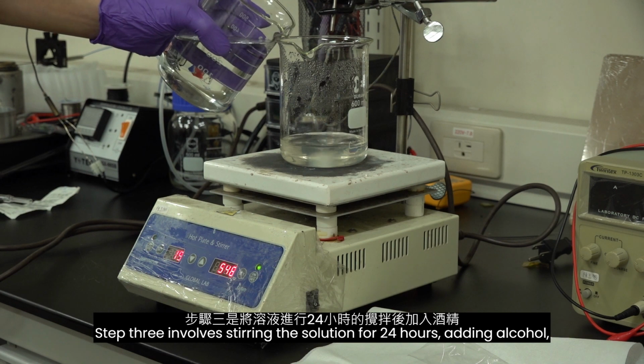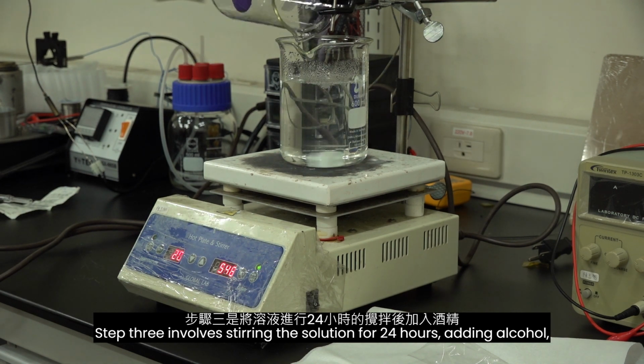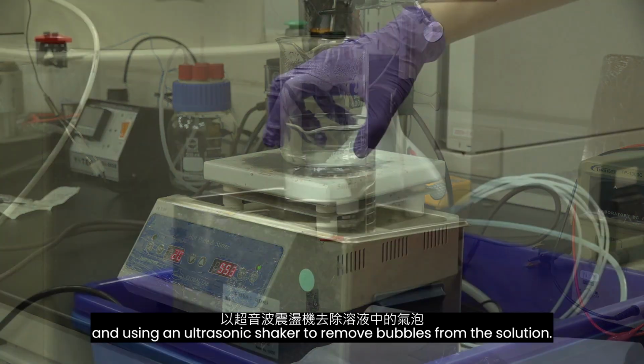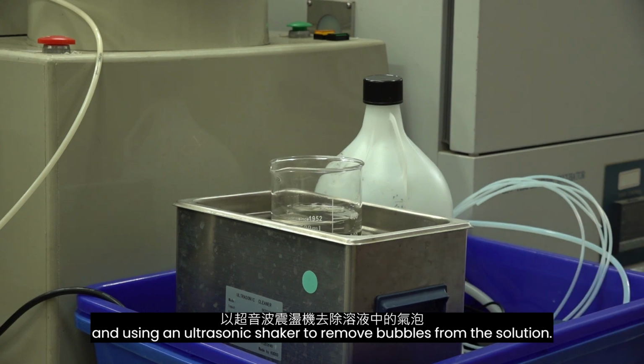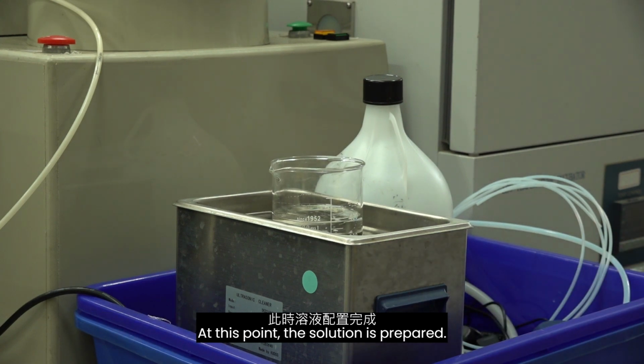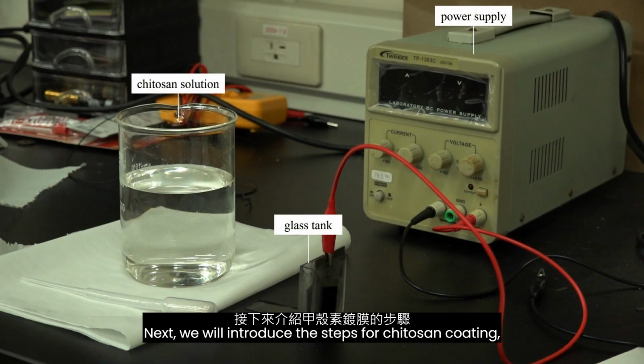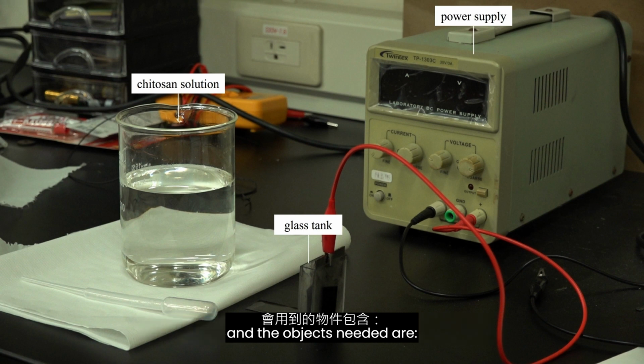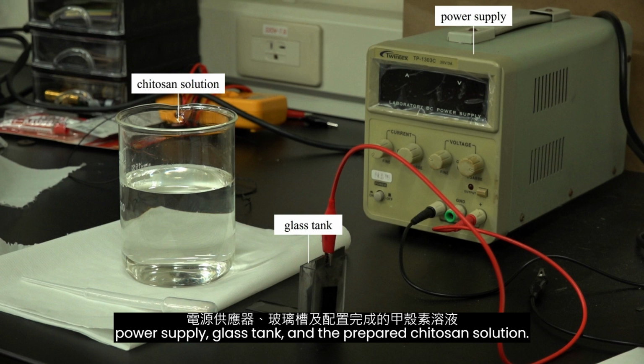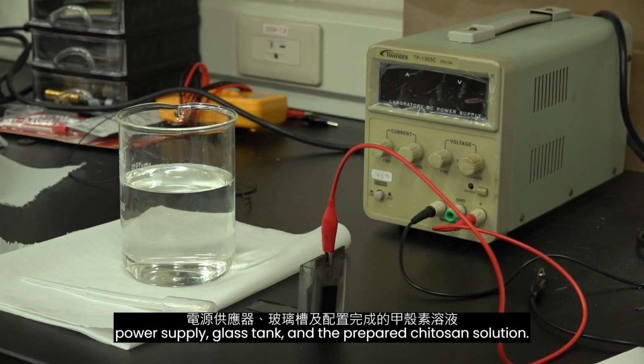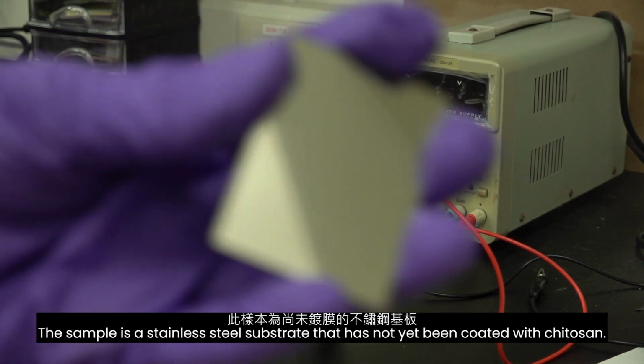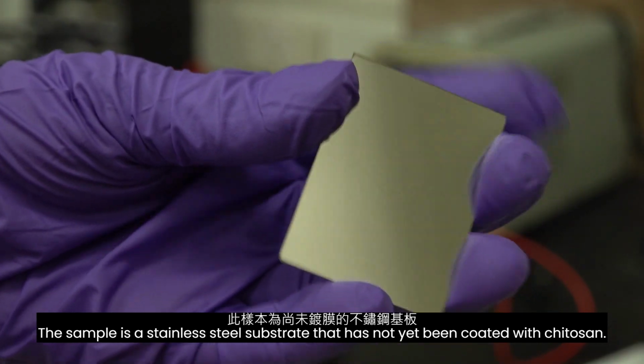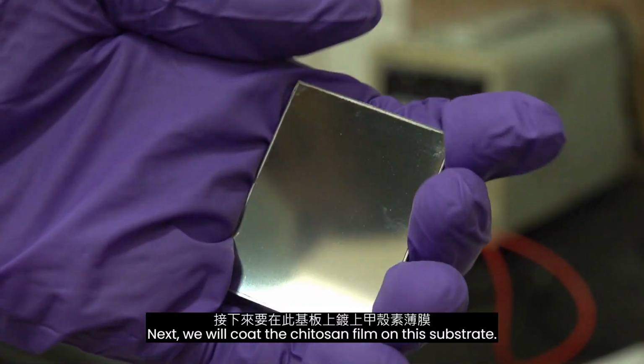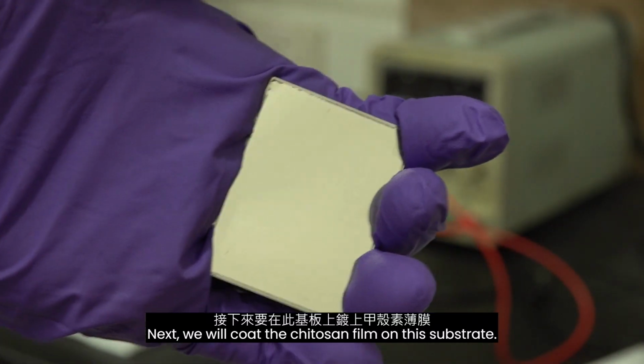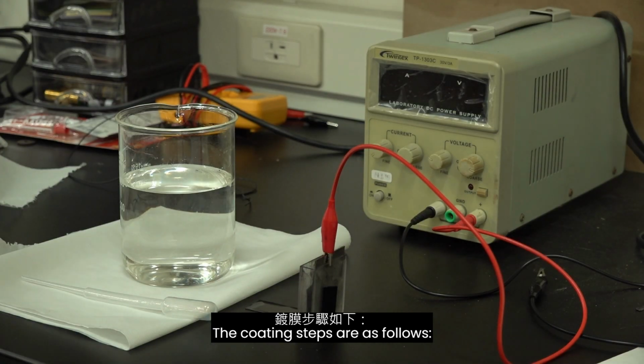Step 3 involves stirring the solution for 24 hours, adding alcohol, and using an ultrasonic shaker to remove bubbles from the solution. At this point, the solution is prepared. Next, we will introduce the steps for chitosan coating, and the objects needed are power supply, glass tank, and the prepared chitosan solution. The sample is a stainless steel substrate that has not yet been coated with chitosan. Next, we will coat the chitosan film on this substrate. The coating steps are as follows.